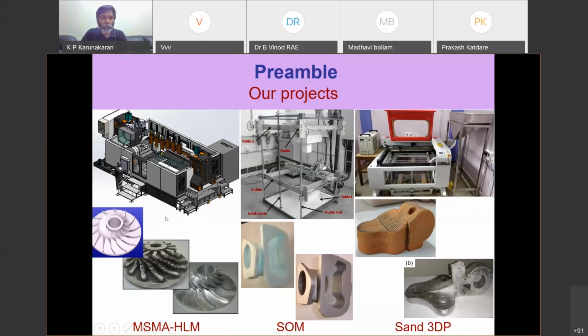Then we also realized that when you have to make components like this, they have a lot of undercuts, but in metal, it is hard to find support structure. So we wanted to eliminate the need for support structure. So we decided to use 5-axis. After all, the need for support is because of gravity. So if we can tilt the substrate such that there is no effect of gravity, then you can eliminate the support structure. So this particular piece that you see here, it was built by tilting the substrate appropriately. So the growth is still horizontal layers, but while you try to deposit the edges, it is appropriately tilted using the Trunnion table.